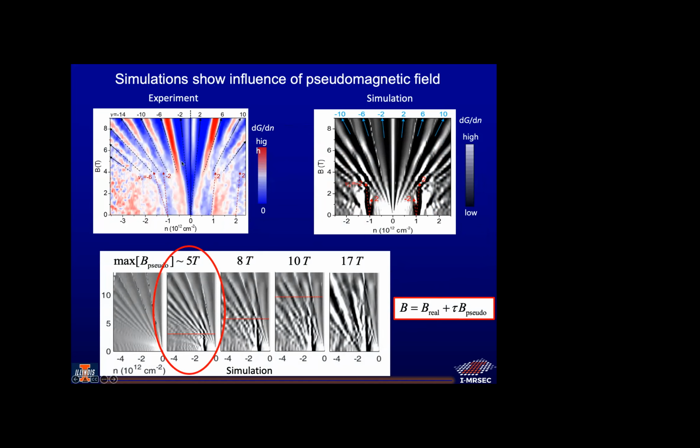So this was, to us, really the first device scale transport measurement evidence of pseudomagnetic fields in these devices, and showing a competition between external and pseudofields in these sort of systems. And again, 5 Tesla might seem small compared to 200 Tesla, but this is on average across a device, which was really interesting to us.